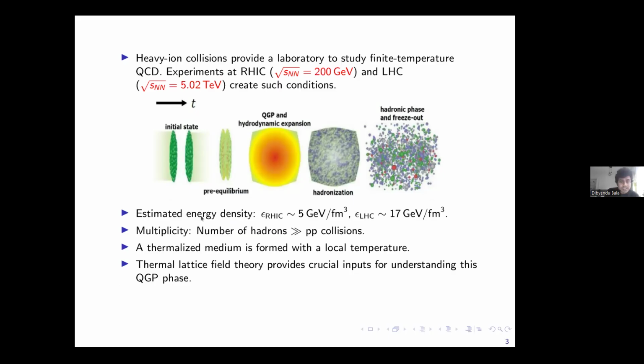And then there is the multiplicity, how many particles are produced. The number of hadrons produced in these collisions is way larger than in PP collisions. For example, at RHIC roughly 8,000 particles are produced, while in a PP collision it's around 200. Because of this large number of particles, a thermalized medium is produced for which a local temperature can be defined, and therefore a thermal lattice field theory will be helpful to study this system.